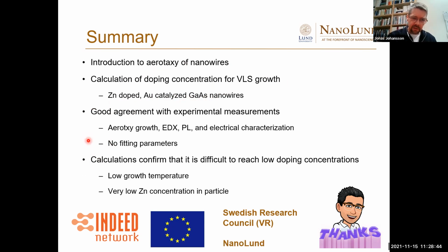And the calculations also confirm something we saw experimentally, that it is quite difficult to reach low doping concentrations. Perhaps due to the high solubility of zinc. So as soon as we put in some zinc, we will get a lot in the particle, and then we will get also high zinc concentration in the nanowires and a high doping concentration.